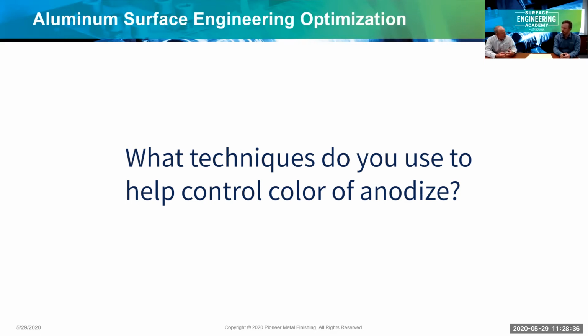So the more porosity, the depth of the porosity, the darker the color that we can make the part. One of the things we've got to make sure that we're doing then to control the color is have the thickness very uniform from part to part and the porosity of the coating be very consistent. After that, it goes back into really controlling the chemistry, making sure that the dye is in good shape. We measure those chemicals with a spectrophotometer, but we've also used the spectrophotometer for measuring the color of the parts too, to make sure that we're meeting the requirements that were set out. From somebody's eye, we turn that into a number as far as what the actual color is.